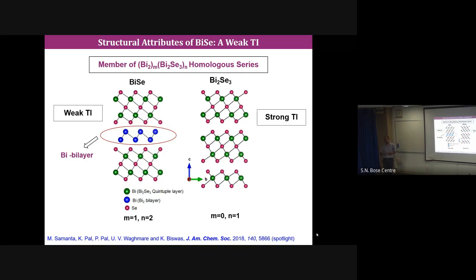And those optical modes again we have seen by heat capacity experiment, low temperature experiment, which shows a boson-like hump as well, which is observed in glasses. So this is a very interesting compound, whose property is actually governed by this layer, which is a heterostructure compound, and this layer gives rise to this weak topological insulator behavior.